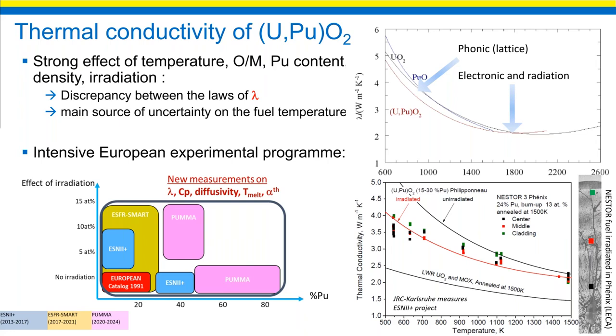So I could spend 2 hours to explain all the different parameters' impact on the lambda of the MOX fuel. You just have to remember that there is a strong effect of temperature, stoichiometry, plutonium content, density, and all the effects due to the radiation. These effects explain the discrepancies between the data and also between the different laws used for the lambda in the different codes. The uncertainty associated with this law is quite high, around 10% for the fresh fuel and around 20% for the irradiated one.